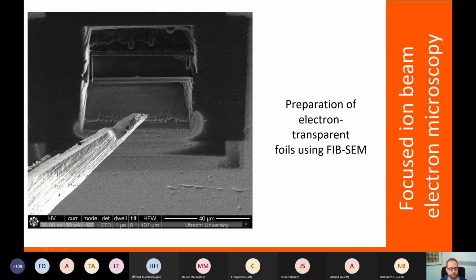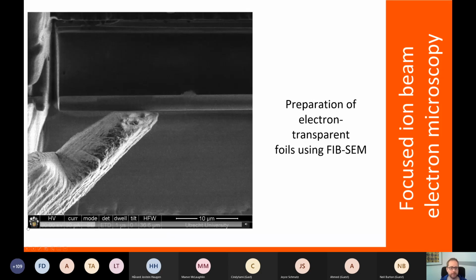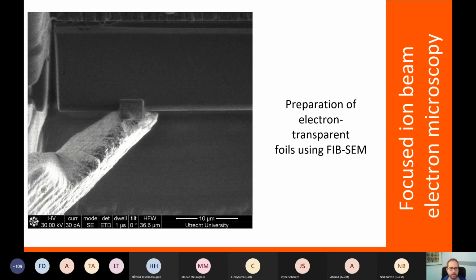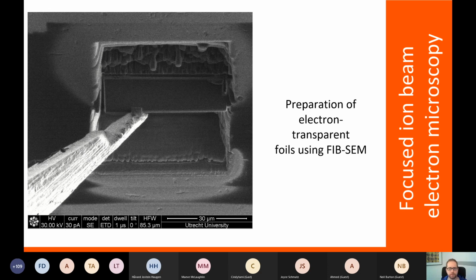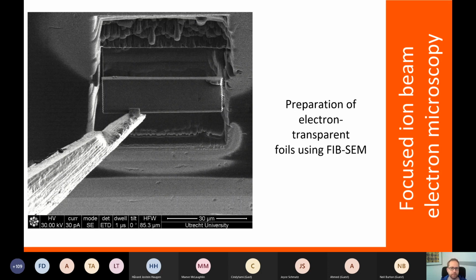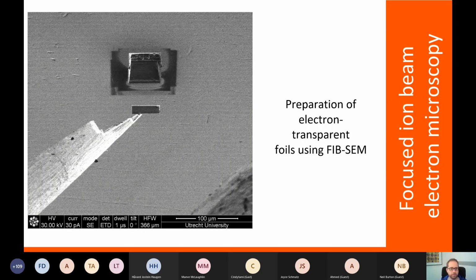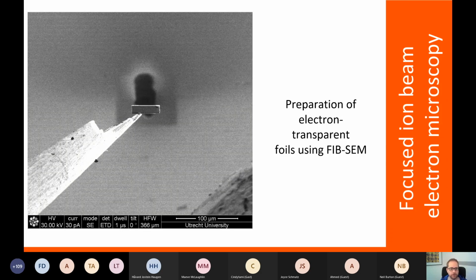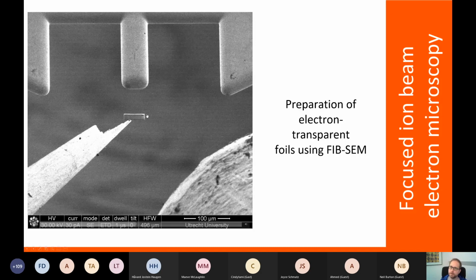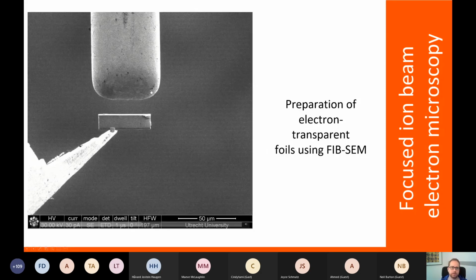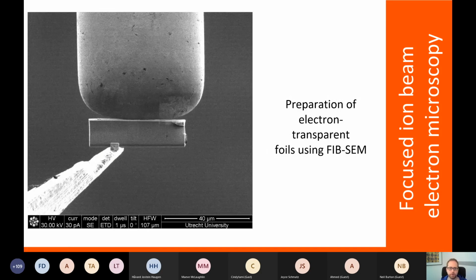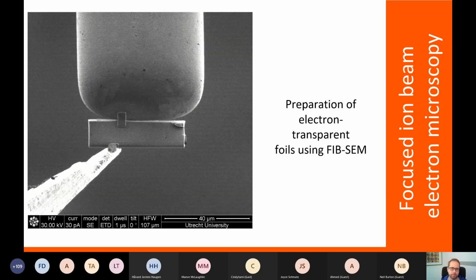This needle now is brought to the sample, and we have cut out this sample at the bottom and on the side and also here a little bit, but we leave a little bit of area left over, so this is stabilized. And now we will approach this needle onto the sample and use the gas injection system to weld the needle to our sample. And then we cut out this little bit on the right-hand side right here. And now we have a sample that we can lift away from our mineral, for example. That is on the order of 15 micrometers by 5 micrometers in this case, but it's still a micron or two thick. We will bring this to yet another holder that we can pick up with tweezers, and we will put the sample onto this holder, welding it again with our platinum gas.